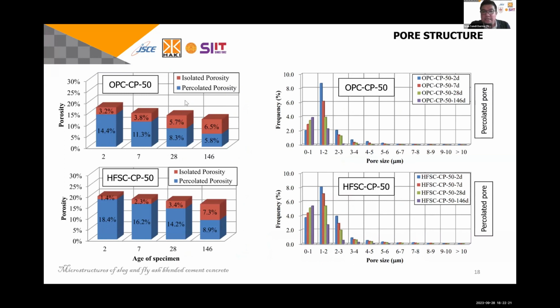And then here you can see the histogram shows the porosity versus curing period. As you can see here, of course, for OPC we will have a lower porosity compared to the fly ash specimen. But again, with the increase in the curing period, the reduction in percolated porosity is higher than for the OPC one.